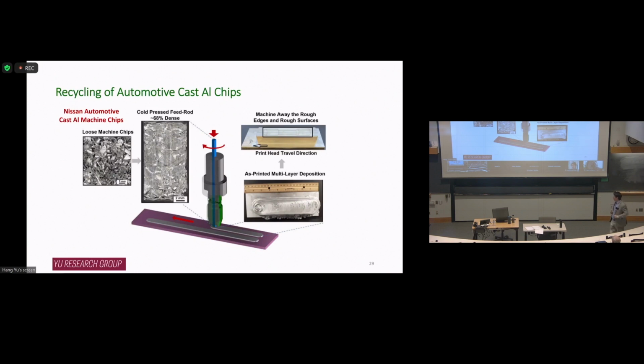We got some machine chips from Nissan. Nissan has some cast aluminum alloy machine chips rich in silicon. We just compress them into the same dimensions as our feedstock. So it's a porous compact with a density of 68%. For this case, we don't have to do any sintering. We just have a porous compact. We insert that into the channel and do a deposition.